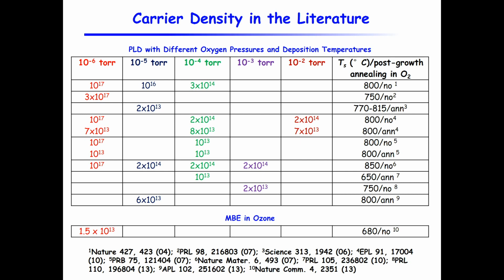Still not what people would expect to have, right? With the annealing, you bring it down, but it's not what you expect. And this is true for other conditions as well. The highest oxygen pressure used during growth is 10 to the -2 from the Geneva group. And so 2 times 10 to the 14, that's about close. But still, when they annealed it, the carrier density actually goes down.